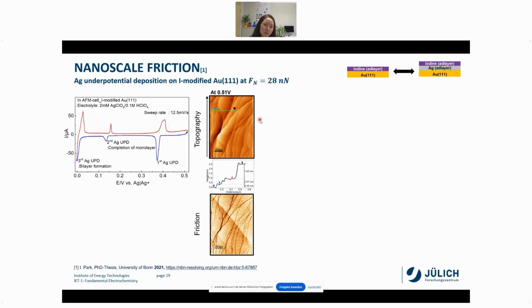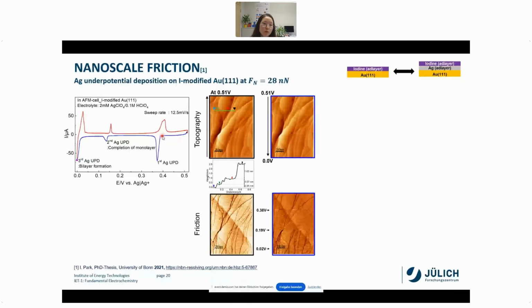At 0.51 volt, before silver deposition, you can see in the topography image that there are large terraces and steps. The friction image matches the topography and additionally shows that friction is higher at the step edge. Remark that the darker color indicates higher friction. And when the potential is swept, this blue line, through the first, second, third UPD peak, the topography shows relatively nothing, but friction shows that something is going on and influencing the friction.